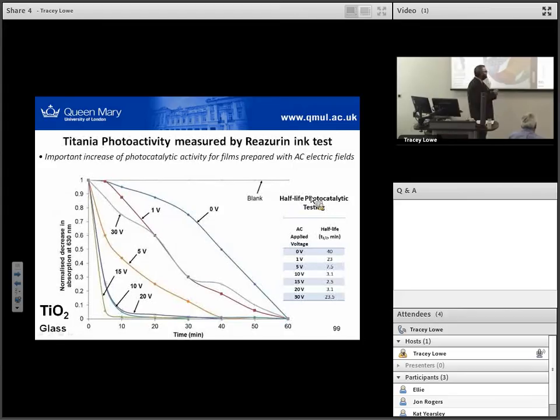If we do this, what we can essentially see is some massive decreases in the half-life, and these peak shapes are not what you would expect from typical first-order kinetics, which is the type of thing we expect. There are clearly several things going on. However, the initial part of the curves can be very, very quick, and this is indicative of these films working well.